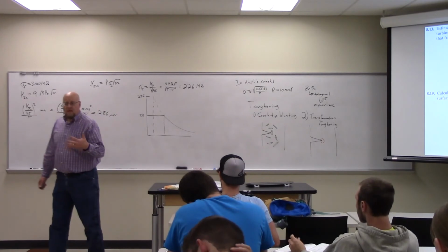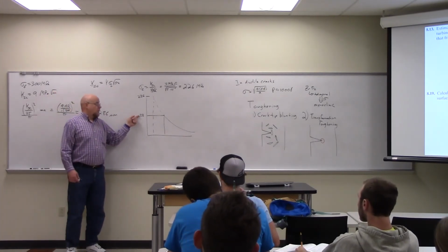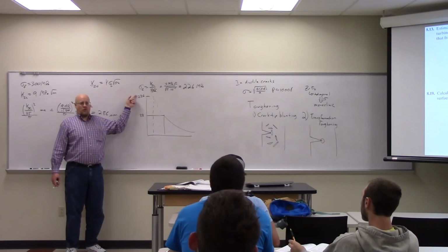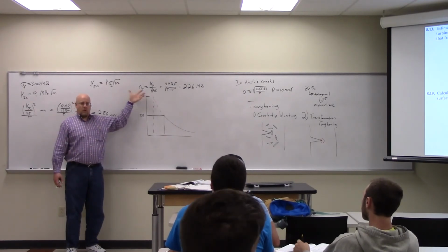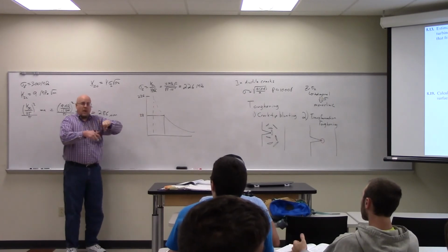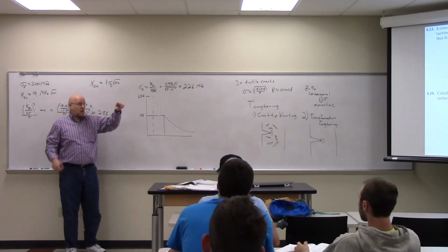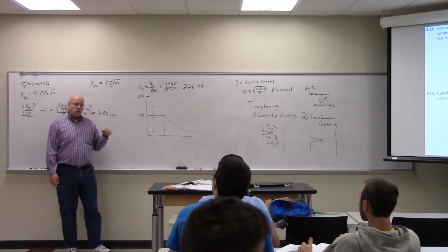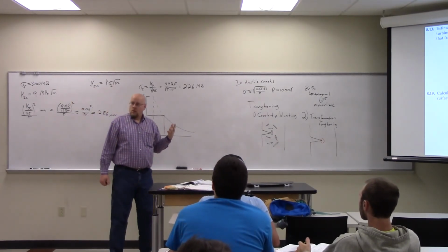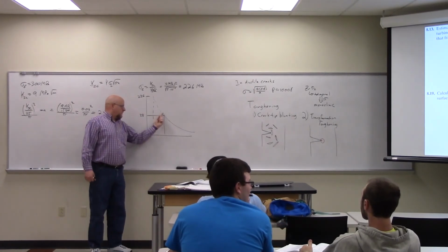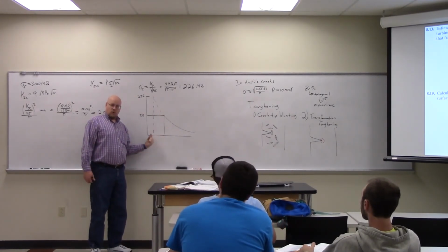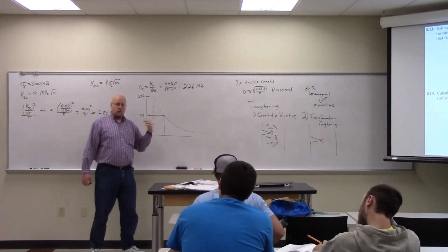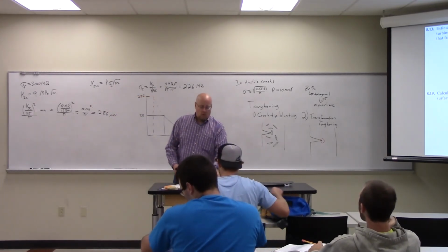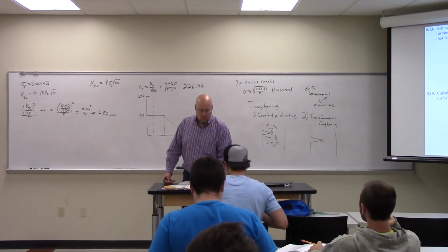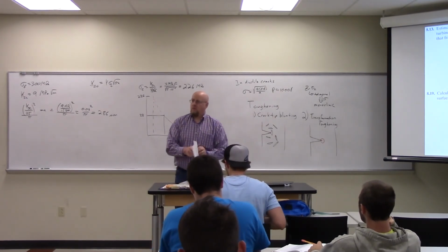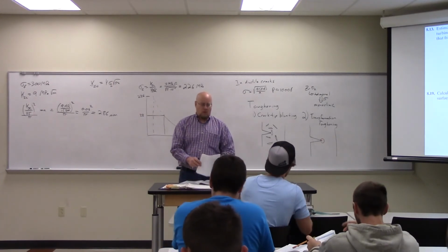So the point is, the ABS itself will fail before that crack causes enough stress concentration to fail it by fracture. If I pull the ABS, it will yield and plastically deform before the crack propagates. Does that make sense? So it's a subcritical defect, below the critical defect size, and we don't care about it. There's no point in polishing a piece of ABS to get rid of 100 micron cracks, because they aren't changing the mechanical quality.